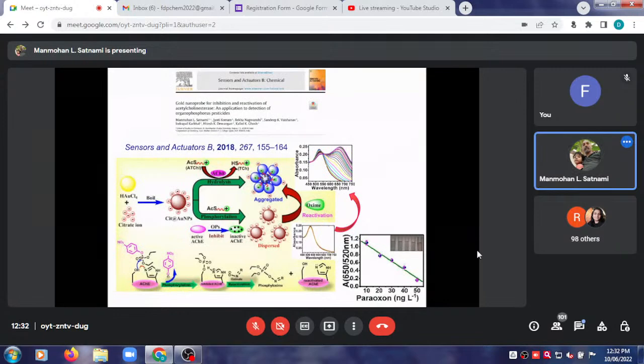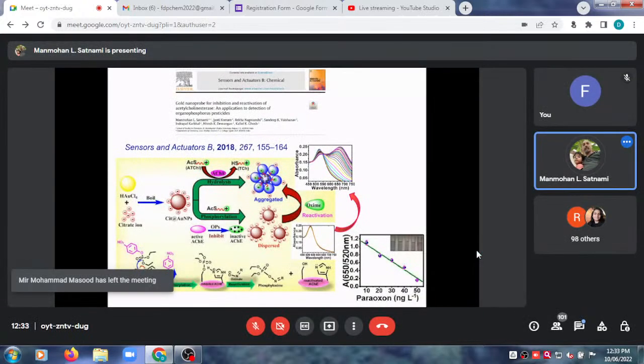Okay, so this is our research work. You can remember that when I began my lecture, I was talking about the UV visible spectra, and I told you that utilizing this phenomenon, we developed one sensor. What we did actually, see, we prepared gold nanoparticles which were capped with citrate. So citrate capped gold nanoparticles were prepared. Then what did we do? We added an enzyme, acetylcholine esterase, to this gold nanoparticle solution, and also added acetylthiocholine.